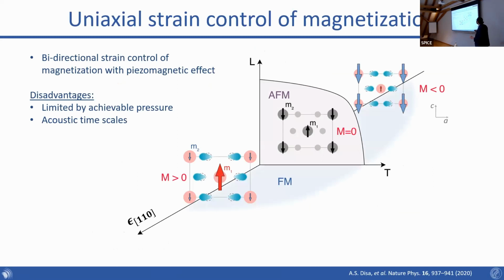And this is quite a useful possible mechanism. It's not the same as switching between domains, but you can imagine this as a way of controlling the magnetic state of the antiferromagnet in two different directions. You can control both the magnitude and the direction of the magnetization by strain. But of course, it has a number of downsides, which is that you have to physically apply a strain, so you're limited in how much you can do before the crystal breaks. And of course, it will also be slow, limited by the acoustic timescale.